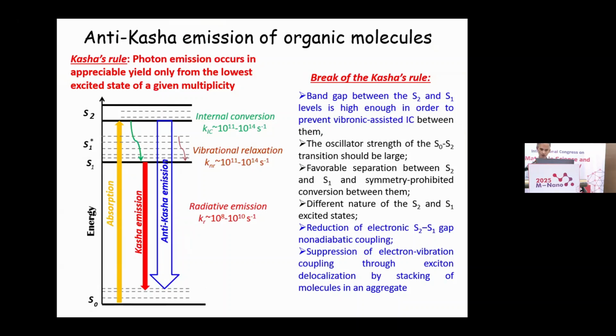In order to realize anti-Kasha emission of organic molecules, as I said, we need specific conditions. Because the Kasha rule doesn't allow light emission from the higher energy levels, since the excited electron on the higher energy level usually immediately relaxes to the lowest energy level, from which the system realizes only Kasha emission. But if we have specific conditions, like a big band gap between S1 and S2, for example, we can try to realize anti-Kasha emission. Also, we can try to realize anti-Kasha emission when we suppress the vibronic manifold in this band gap, because vibrational modes are responsible for the fast relaxation of the excited electron from the higher energy level to the lowest energy level.